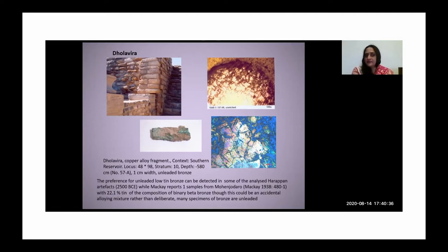Now, I'm taking you back in time to Dholavira, which I had touched upon earlier, of course. I was given a fragment of copper alloy by the ASI and Dr. Bisht and so on at that time, which was from the southern reservoir area, to analyze. And that is actually unleaded bronze, but it's low-tin bronze. It's not a high-tin bronze. It's a low-tin bronze of about 5% tin, and it has those equiaxed grains that you'd expect in a solid solution. Now, I should also say that it's a bit confusing because sometimes when bronze is cold worked, it has these kinds of lines which form.